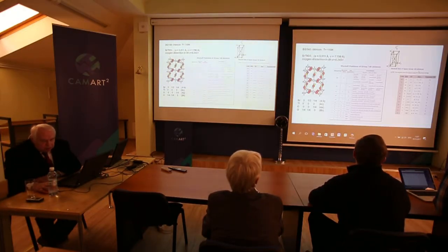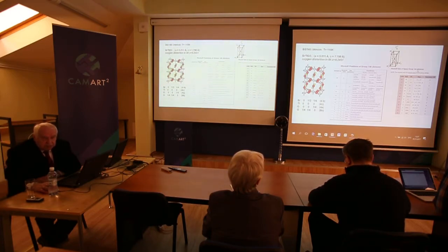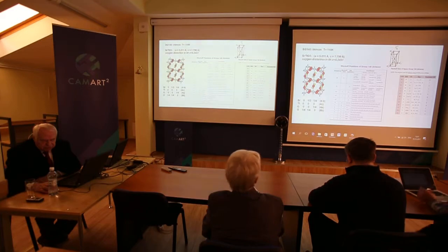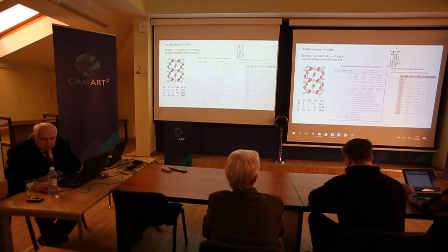So you see, the space group of the low temperature phase is I4/mcm. What does it mean? It means that this is a body-centered tetragonal lattice, with a reflection plane orthogonal to this fourth order axis. And then this is a non-symmorphic group. I'll speak about it in more detail on the rutile example, what non-symmorphic means. When you have here c or b or a or an axis with some small number, not in this case, near the axis order, I'll demonstrate it on rutile, then you will understand what it is.